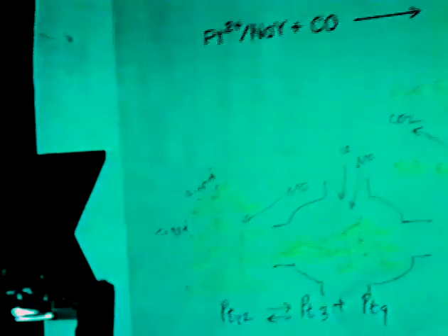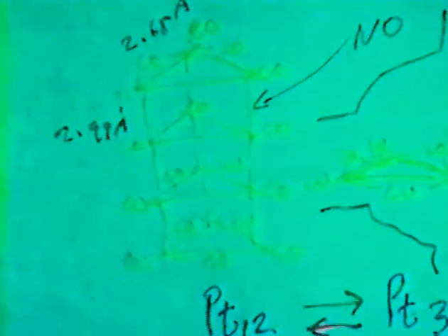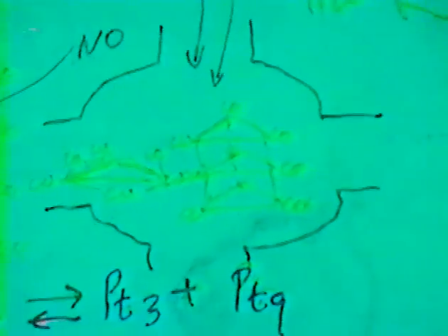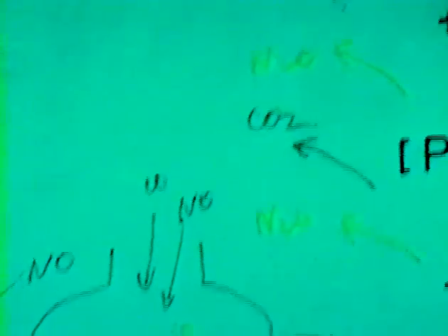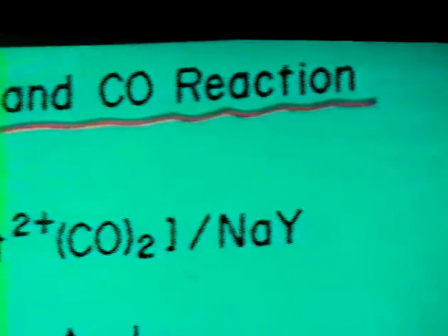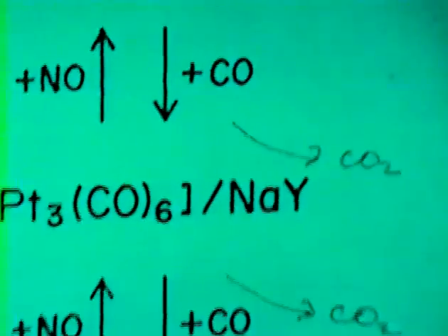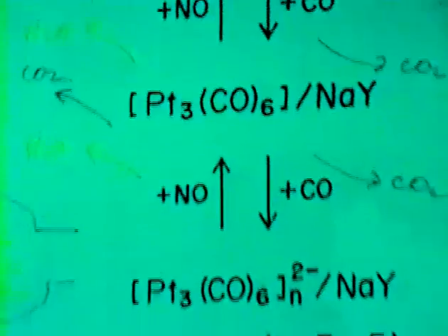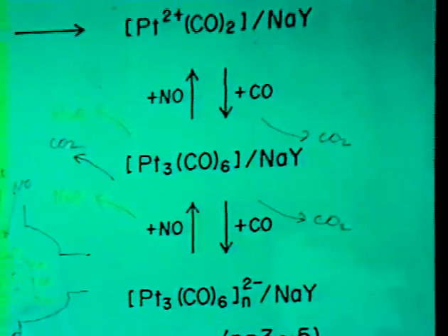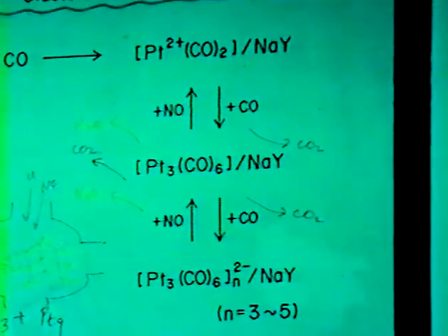From these data, we suggest that the NO, nitrogen oxide, specifically breaks the intra-planar platinum bond, and eventually the intra-triangular platinum bond, making fragments of carbonyls. The carbon monoxide revealed that these clusters re-form the platinum bond.